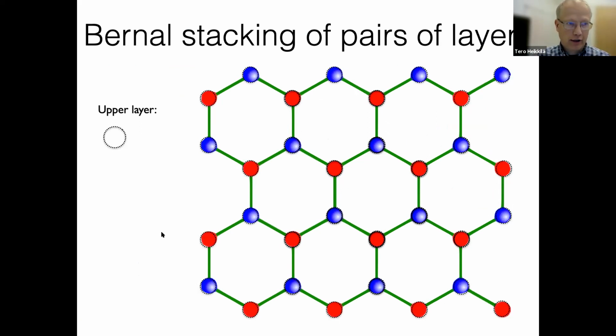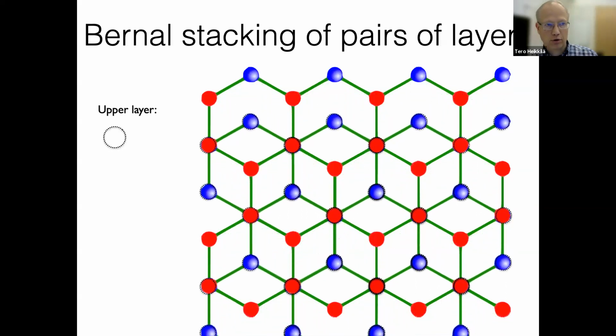But okay, how you get there is that you want to stack graphene layers, and the way you stack every pair of layers is this so-called Bernal stacking, where you take the two layers and then you shift, so that, let's say, the graphene lattice consists of this blue and red atoms, meaning just that the unit cell contains two carbon atoms. So in the other layer, the blue atom goes on top of the hexagon, and the red atom goes on top of the blue atoms of the previous layer. This is the so-called Bernal stacking, which is the most stable one.